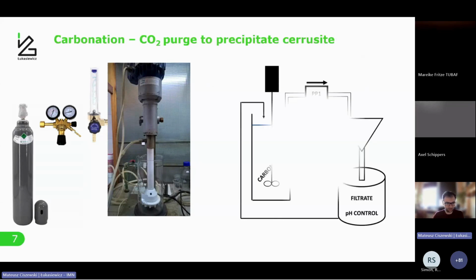Carbonation at lab scale was done in a flotation machine with a proper volumetric flow rate of carbon dioxide. Of course, at pilot scale, it was done not in a beaker but in a big 3 cubic meter reactor. At lab scale, every 15 minutes the filtrate was checked to see whether lead ions were still present. That's how we found at what pH the depletion of lead ions is practically finished.